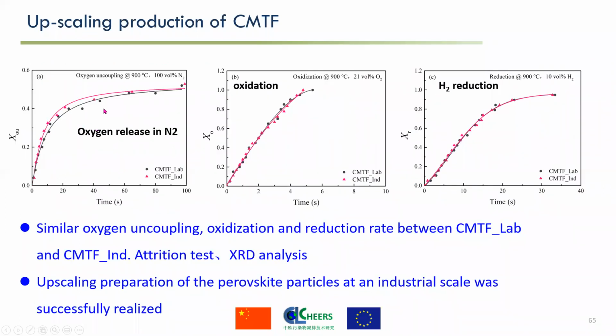Then we studied the industrial scale CMTF's kinetics and compared it to the lab scale CMTF. We find the industrial scale CMTF has very similar oxygen release rate, oxidation rate, and reduction rate to the lab scale CMTF. Also, the attrition rate and the XRD results are very similar. So the upscale production of CMTF is very successful.